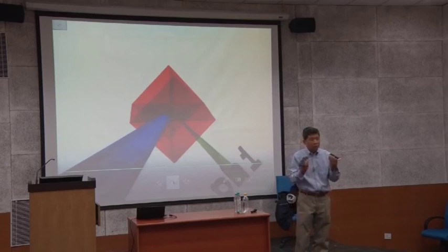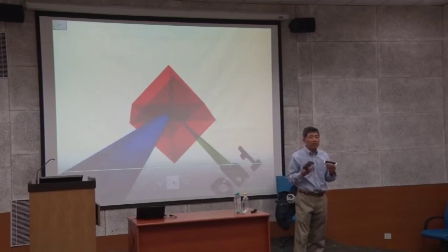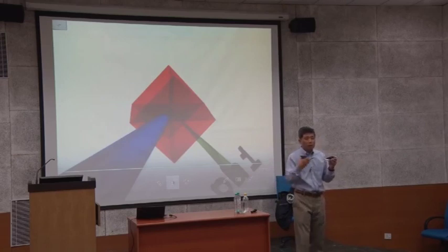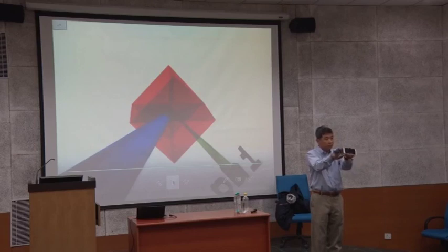Okay? So the other one is that some of the superconductivity people make bicrystals, growing films on bicrystals and measuring the transport across the grain boundaries. The way they make the bicrystals, you take perfect crystals like this, polish them at a certain angle and fuse them together. So this one is misoriented like this.